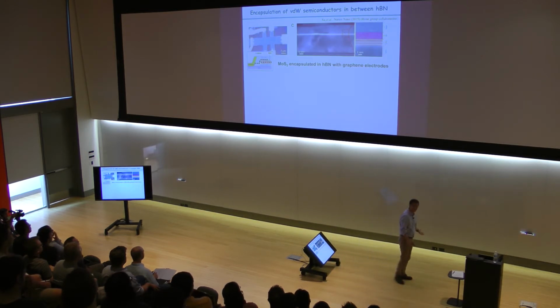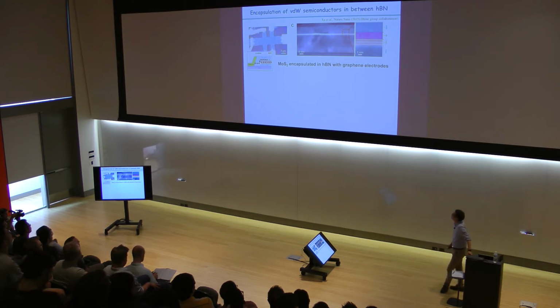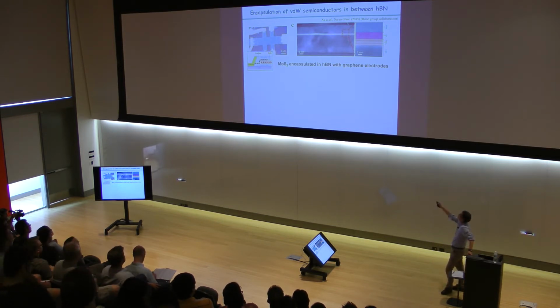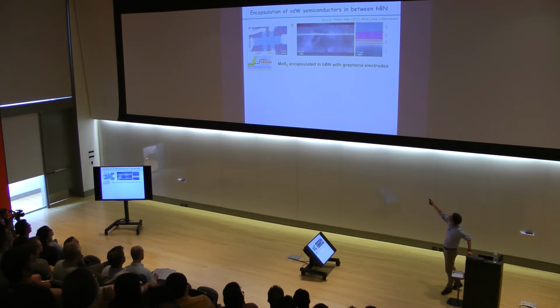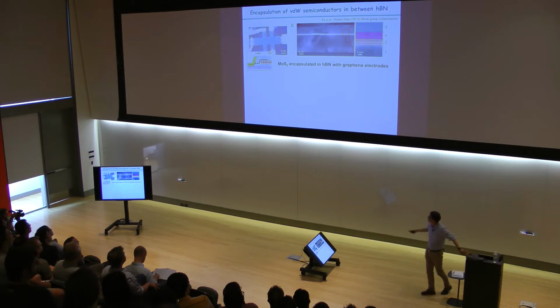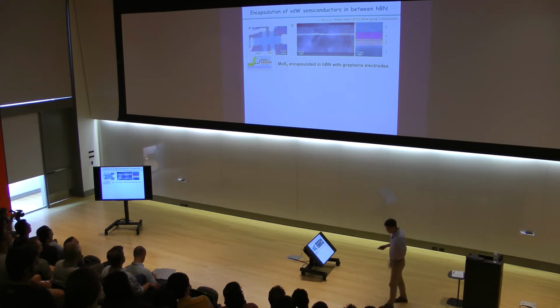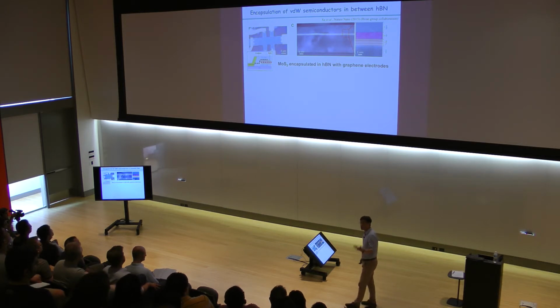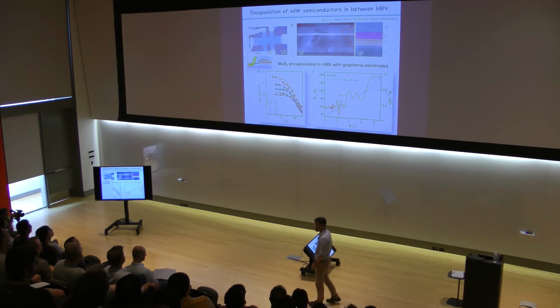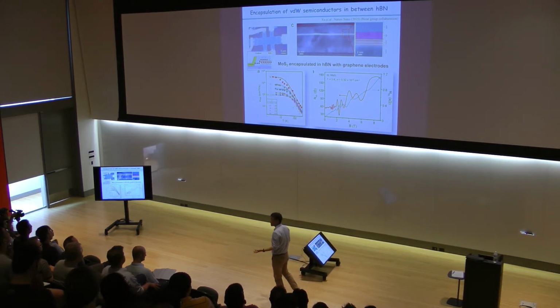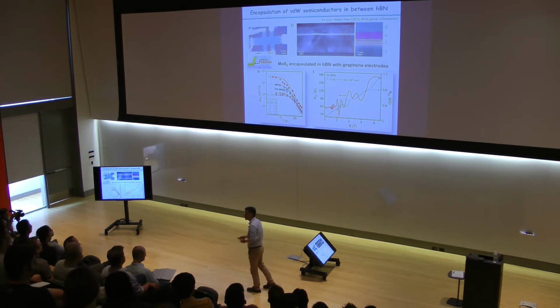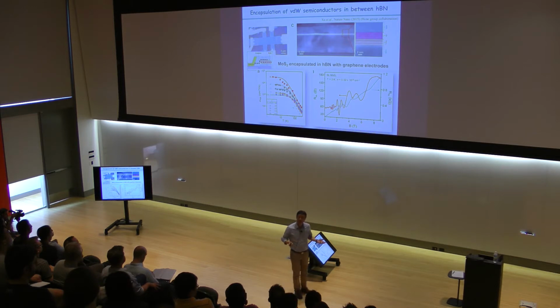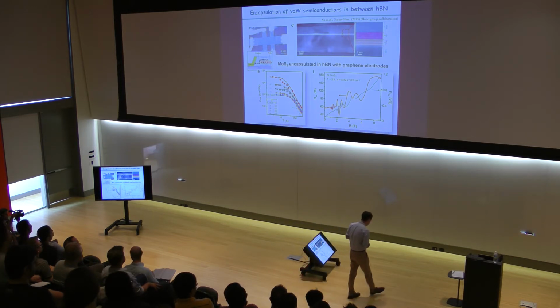It's not only graphene, but you can make all these heterostructures in various semiconductors and other systems. In this particular example, we have boron nitride, graphene, and molybdenum disulfide encapsulated in between boron nitride to make the heterostructure. The graphene onto the molybdenum disulfide makes a good contact between them. So graphite, in this few-layer graphene, serves as a good contact on molybdenum disulfide, and nevertheless, molybdenum disulfide is encapsulated in this boron nitride, which gives us a really good channel, and the entire structure can work as a transistor, and the mobility is quite good, something like easily 10,000s. Under the magnetic field, they show quantum oscillation again. So you start to see that this example actually extends beyond graphene. One can make these kinds of interesting quantum devices as well.